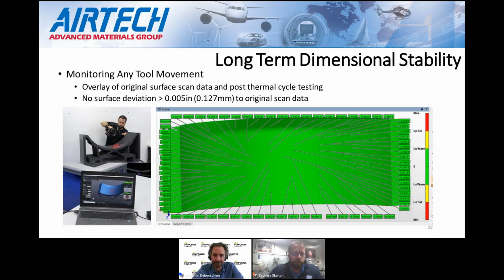Again, looking at the long-term dimensional stability. We do have a very detailed test report that we can provide to customers. Feel free to reach out if you'd like to see it. But this was an overlay post-cycle testing to the original scan data. So no surface deviations greater than 0.005 of an inch. You can see the overlay there.